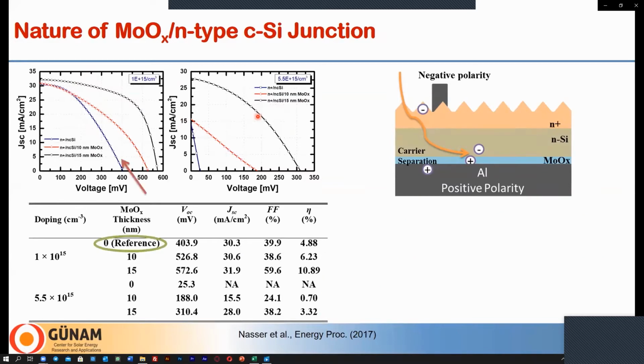For the cell with moderately doped wafer, as you can see here, the molybdenum oxide free device. So the device without molybdenum oxide resulted in very low efficiency. This result was expected because the silicon aluminum Schottky junction cannot effectively separate carriers, as well as there is the presence of high defect density at this interface.